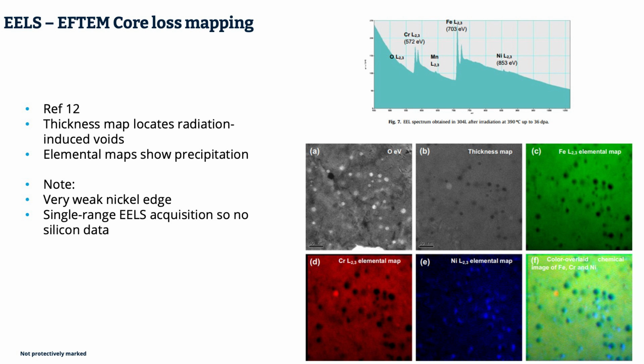This example uses the EELS spectrometer as an energy filter on an image. So you acquire an entire image at once, and by acquiring images, let's say at this energy loss and this energy loss, you can extrapolate the intensity under an edge. If you take another image directly under one of the ionization edges, you extrapolate the intensity from that and you're left with essentially an element map. And that's been done in this case for iron, chrome and nickel in this irradiated stainless steel. It's showing the enrichment of nickel and the consequent depletion of chromium and iron around radiation-induced voids and dislocation loops.